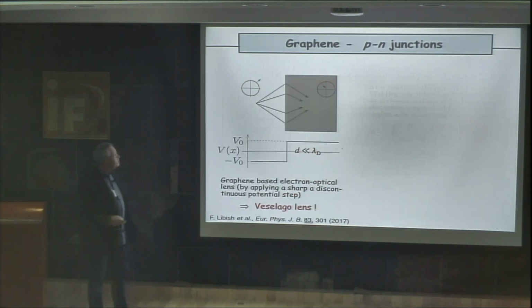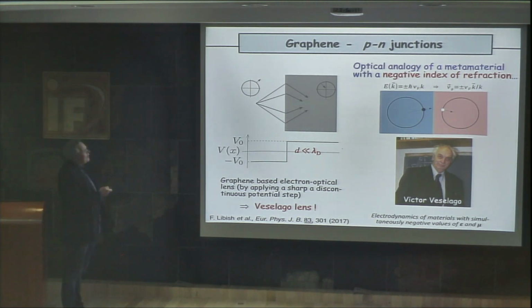What does that mean? This means that you can use graphene, especially a p-n junction in graphene with a very sharp transition like this, as a lens. A lens, because if you start from this point here with your electrons, you have electronic trajectories that are diverging from this point, and when you reach the p-n junction, suddenly they refocus to a focus point which is here. Okay? And this is due to the fact that your group velocity changes sign. So you have an optical analogy of a metamaterial with a negative index of refraction.